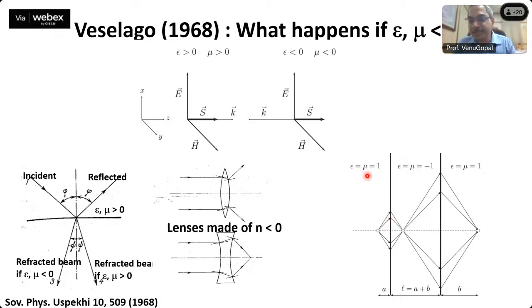However, because of the shift from positive to negative index medium, the high k vectors are now propagating inside this, and then they get focused inside the medium. And then after that, they again start diverging. And again, at the second interface, from negative medium to positive medium, they'll again start converging because the sign of n is changing.